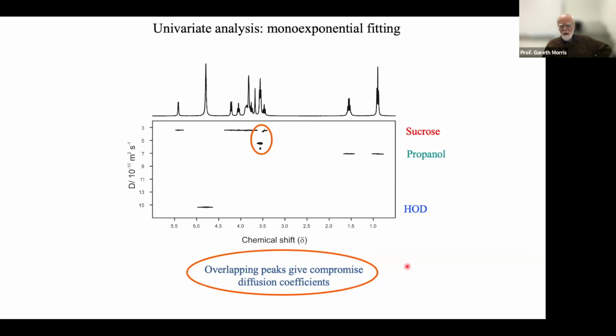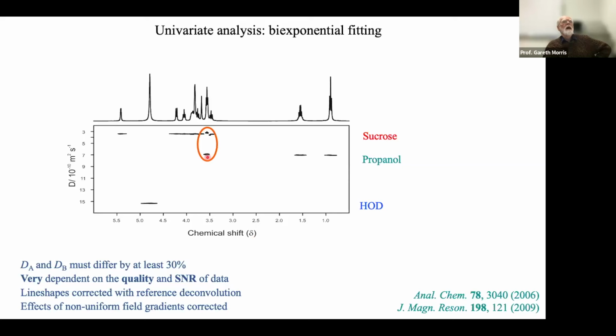And we do that here, and we get a reasonable result. It's not perfect, but it's pretty good. But our diffusion coefficients here differ by more than a factor of two. Now, if you do experiments with different D ratios and different signal-to-noise ratios, what you speedily find is that you need really good signal-to-noise ratio to disentangle two decays, even if they're a factor of two different in diffusion coefficient. And the furthest you can get with the best possible data is typically about 30%.